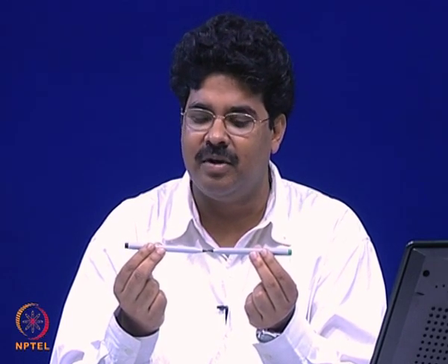Now, if they get terminated by a coupling reaction, the polymer which is formed here will have a degree of polymerization, or the total number of monomers present in the chain, of twice nu. Now, if these two propagating radicals collide, interact and get terminated, forming dead polymer by a disproportionation reaction, then you get two dead polymer chains, which will again have the same number of monomer molecules which were present in the chain before the termination reaction.